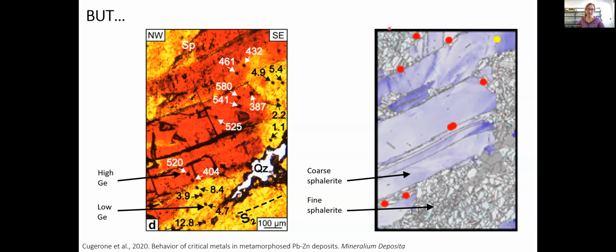Now, the image on the right is the same area, but with the grain boundaries marked in gray. So you can see that the high germanium area, that's over here, is really coarse-grained. And in this case, that's primary hydrothermal sphalerite with high germanium. The low germanium areas, like this, are really fine-grained. And in this case, that's recrystallized sphalerite. So this suggests that the dynamic recrystallization of sphalerite expels germanium. And that's really important if you're trying to extract germanium from your sphalerite mine, or if you're going out looking for good deposits to mine for germanium.